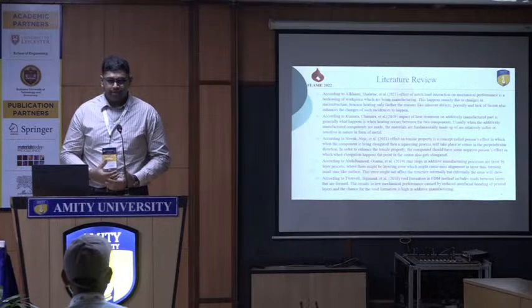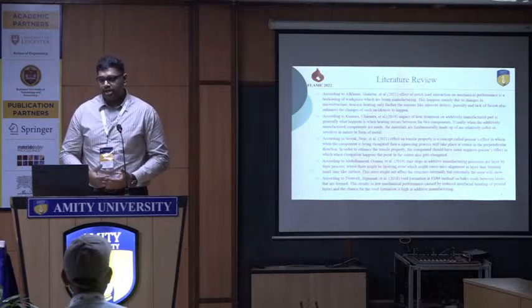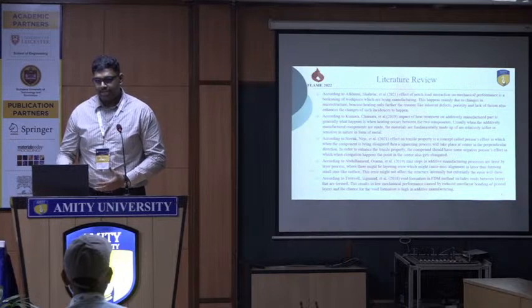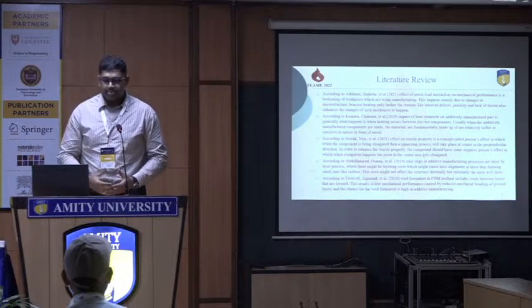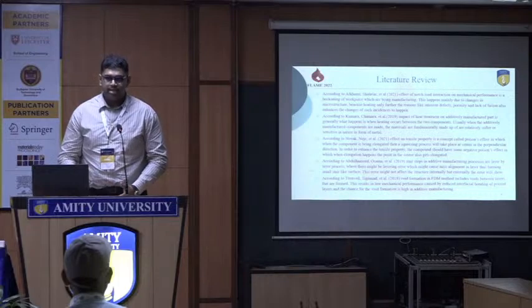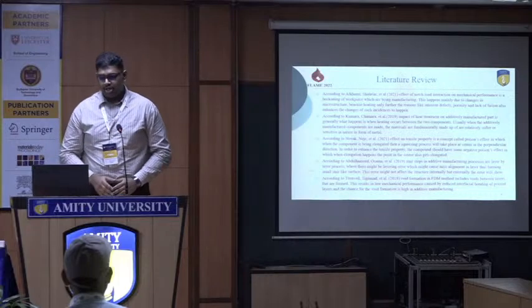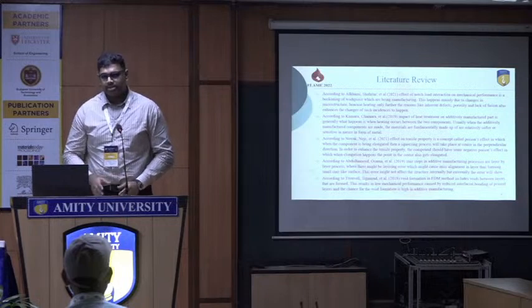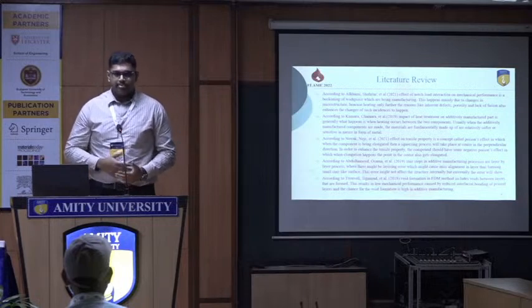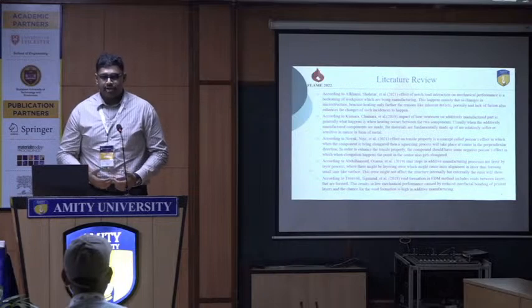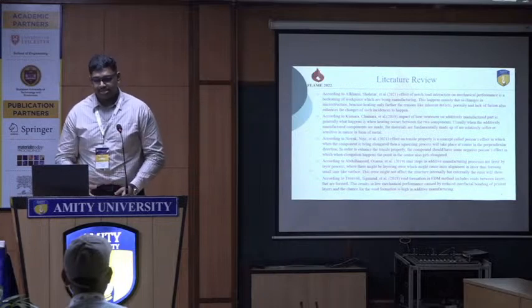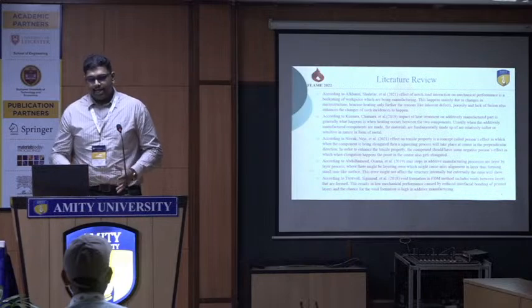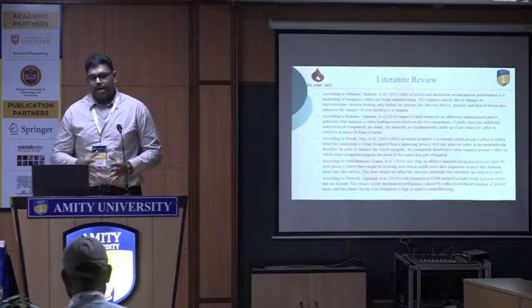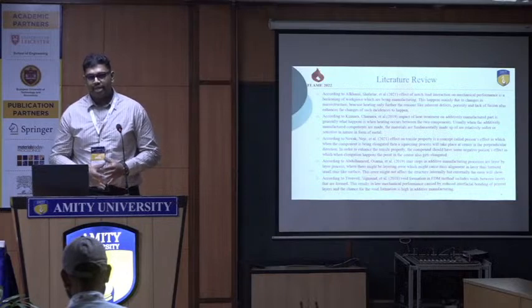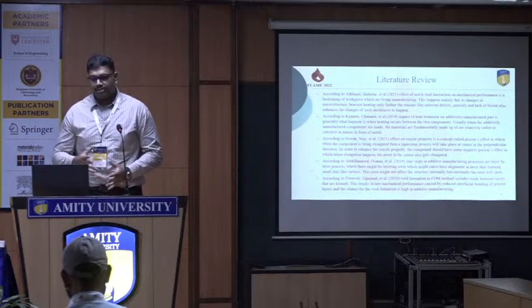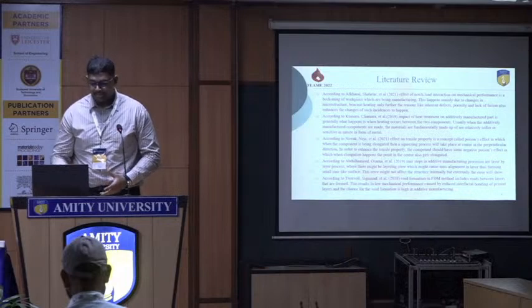And next we have void formation. Void formation is an issue found mostly in the FDM manufacturing technique, and this is due to the fill densities that vary. Usually for FDM, for a locally produced good, we go from 25% to 75%, and as we want to increase the product life, we go from 75% to as much as we can. These actually control the voids in the product, and in large-scale manufacturing, we'll have time constraints, so sacrifices on the fill density are made.